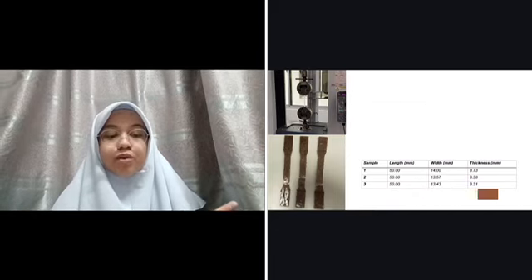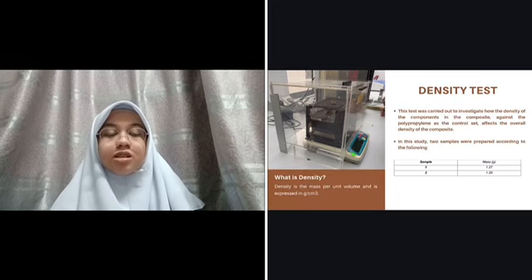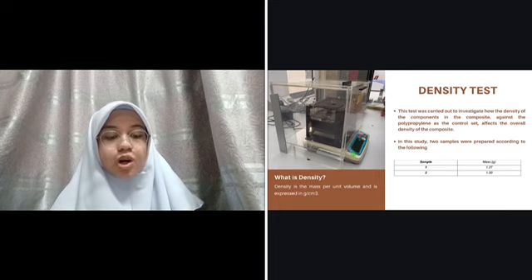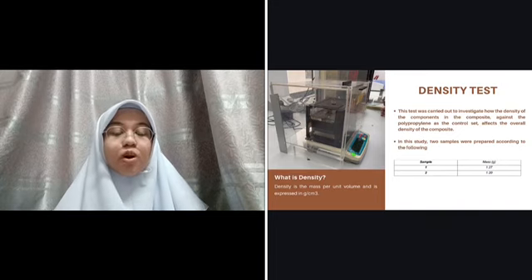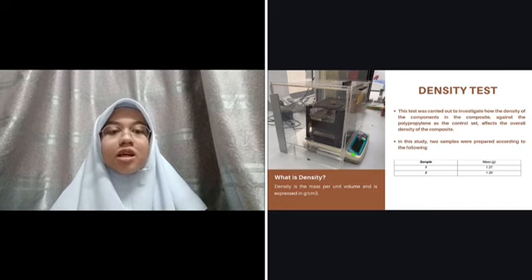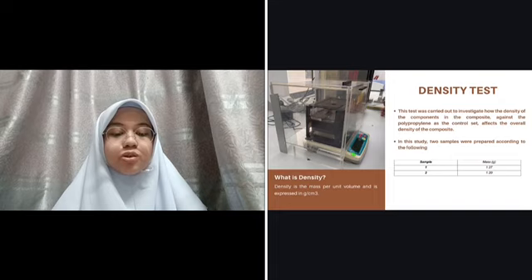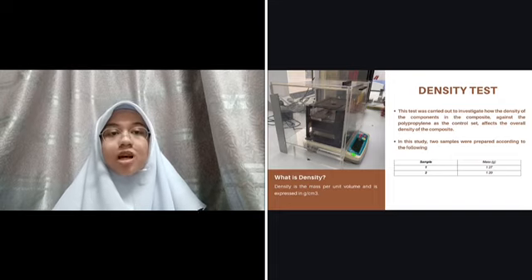Next, we carry out the density test. This test was carried out to investigate how the density of the components in the composite against the polypropylene as the contrast will affect the overall density of the composite. So we used the machine from the University Technical Malaysia Malacca to carry out this test. And we prepared 2 samples with different mass to conduct the test.